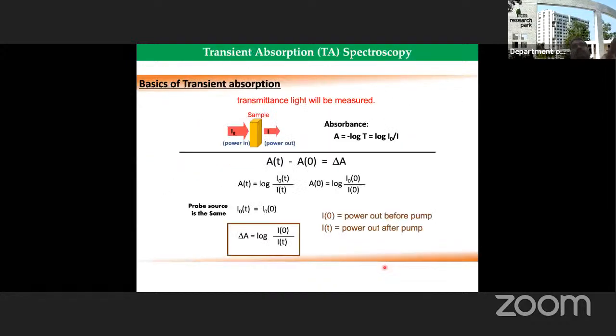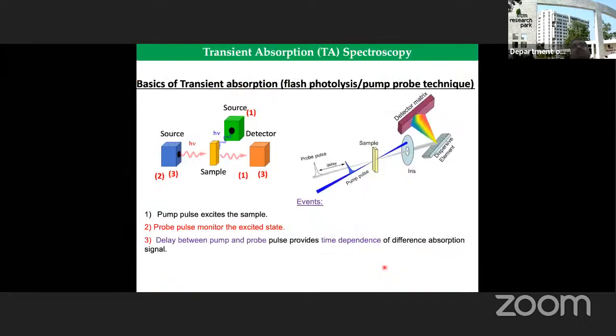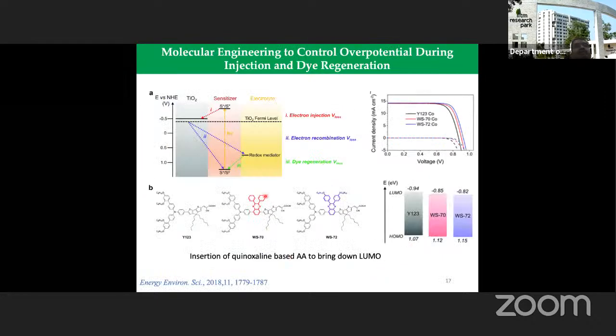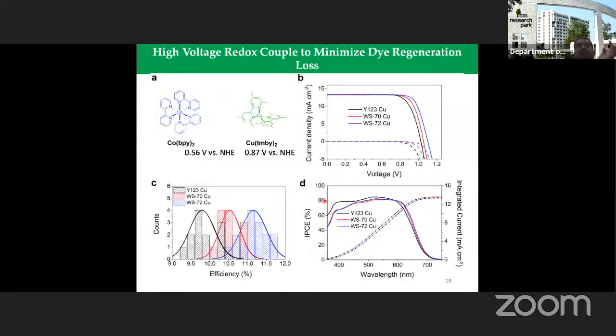What is the molecular design here? If you see carefully, this fellow quinoxaline, when you put it, the recombination time is increased to 9.5 milliseconds. But when you attach this alkoxy substitution, it further increases. That means this alkoxy substitution somehow delays the recombination of the electron in the TiO2 to the oxidized dye molecule. That's called molecular engineering, where we make changes in the structure so that we get the desired property.